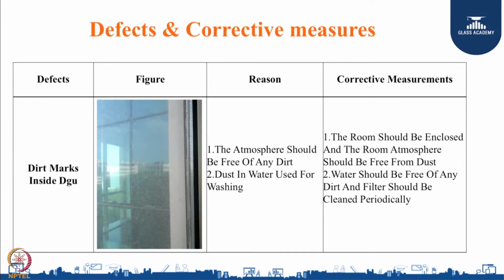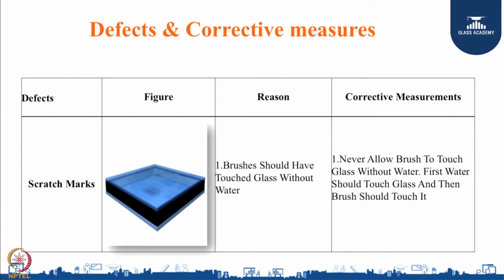Dirt marks inside unit, double glazing unit. Reason is the atmosphere should be free of any dirt, dust, and the water used for washing too. Corrective measure is the room should be enclosed and the room atmosphere should be free from dust. Second is water should be free of any dirt and filter should be cleaned periodically. Scratch marks. Reason could be brushes touched glass without water. Corrective action is never allow brush to touch glass without water. First, water should touch glass and then brush should touch the glass, and you can avoid scratch marks.